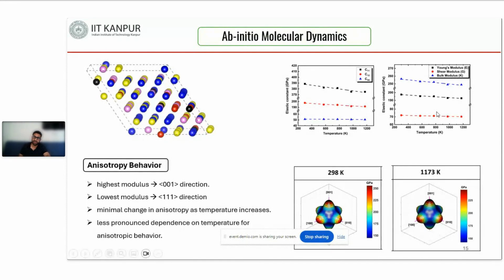Once we got the second order elastic constants, we tried to calculate the anisotropy behavior. When we predict this anisotropy behavior, we find that the modulus is high along the 001 direction and low along the 111 direction. But if you see the outcome, at 298 Kelvin and even at 1173 Kelvin, the change in anisotropy is very minimal. So we can say that the temperature dependency of anisotropy is very minimal for this alloy. So it is showing a better property and less temperature dependence.